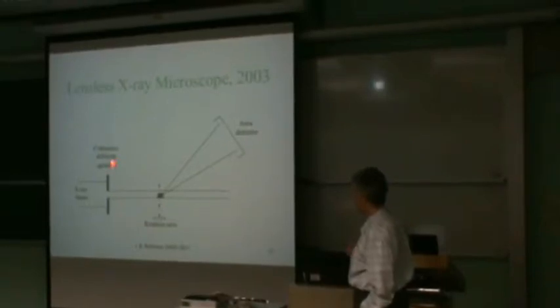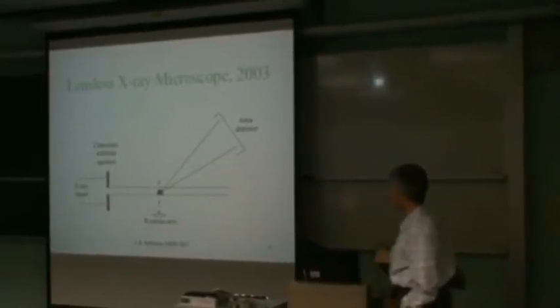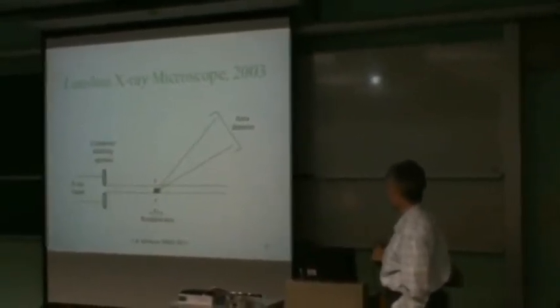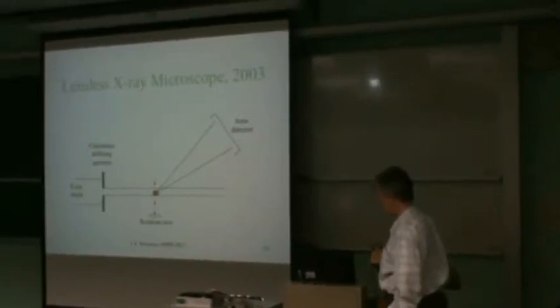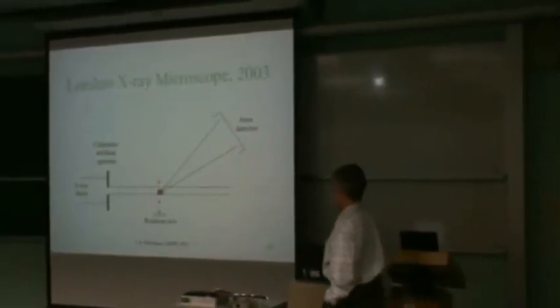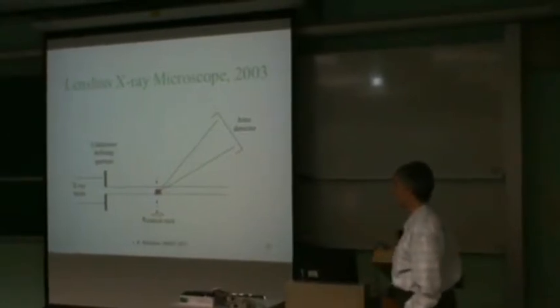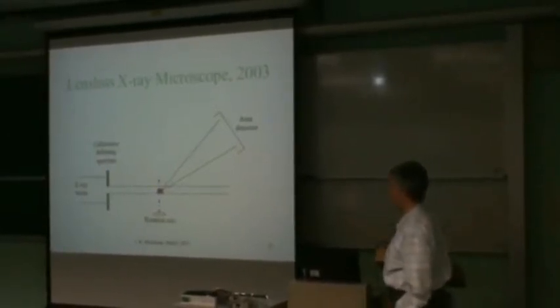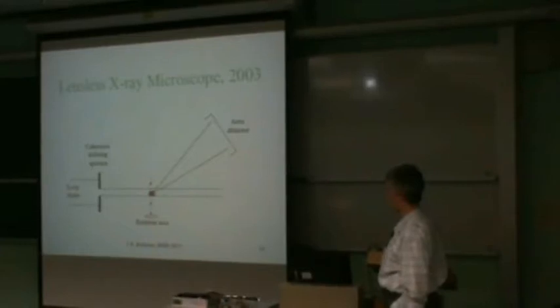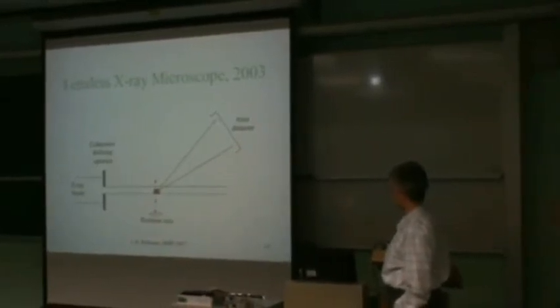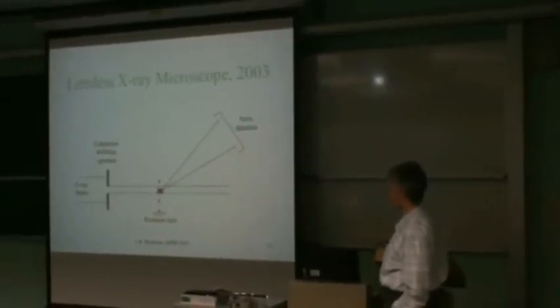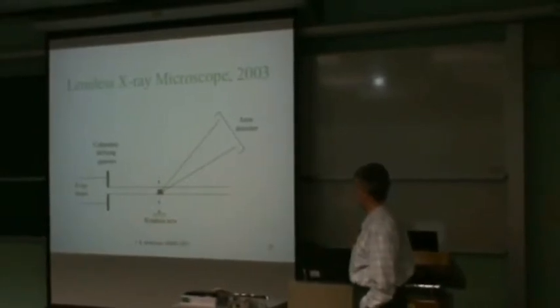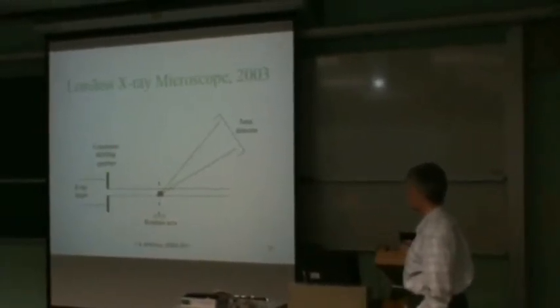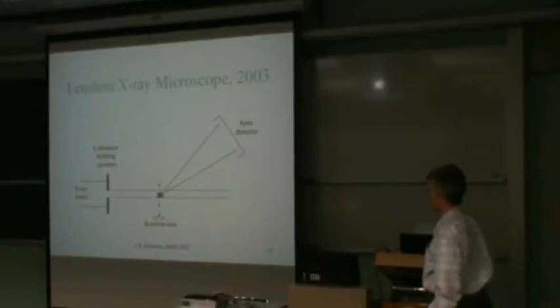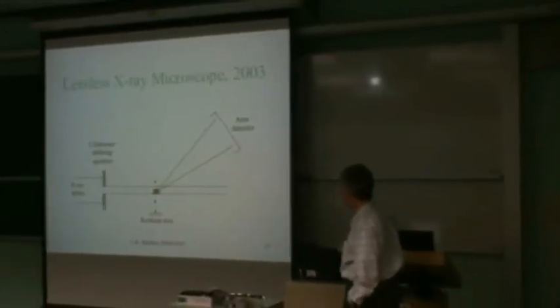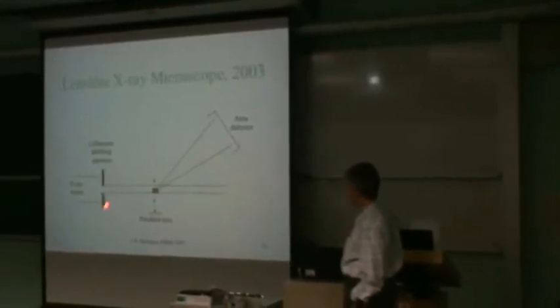This is a big waste, but the source is only about 1% coherent, and so we throw away 99% of it. In the not too distant future, the sources are going to be upgraded, starting with the ESRF in Grenoble and then hopefully at Argonne as well. And they will be able to get up to, for hard X-rays, up to about 50% coherence. And so this will be an enormous improvement to the experiments coming along down the road. But right now we work at about 1%.